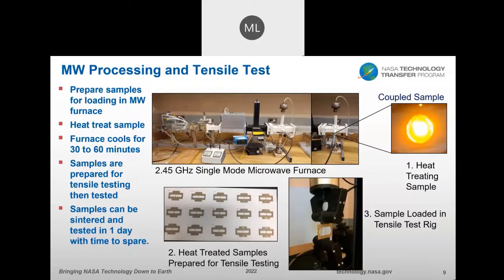So in our case, the process was really quite simple once we worked out all the hard details. Here you can see our furnace in this upright picture, where you see the coupled sample. That's where the sample is loaded. So typically we prepare the samples for loading in the microwave. We heat treat the samples. The furnace cools in about 30 or 60 minutes, sometimes sooner or later, but it's about an average of an hour. Samples are then prepared for tensile testing, then tested. So samples can be sintered and tested in one day, with time to spare for other exciting things in the research life of a scientist. Okay, next slide.